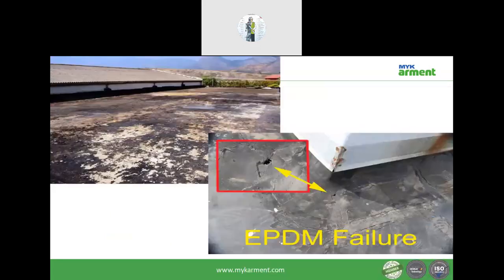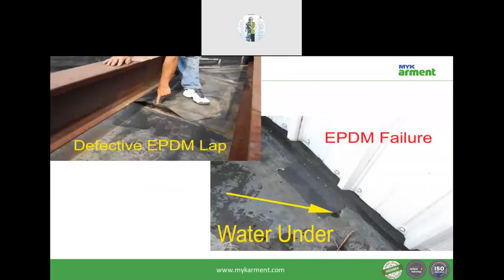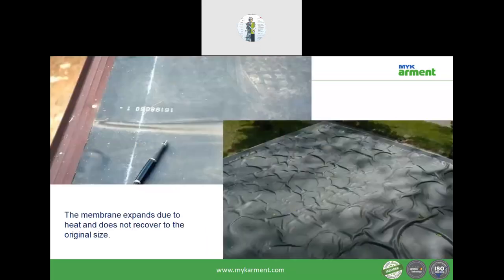This is another problem. If EPDM has been used, these are the failures because of the damage: the EPDM laps and joints open up, and that would be the source of the water seepage. Then you have a lot of water seepage on the slab, and you will never know from where the water is seeping in. And this is another typical example. If the membrane expands due to the heat and does not recover, this is because of improper selection of the waterproofing system. Due to the thermal effect, it wrinkles.